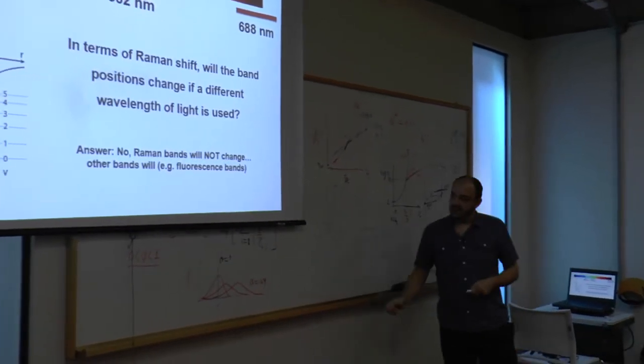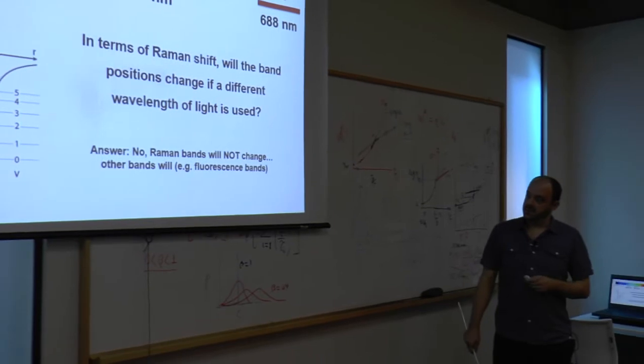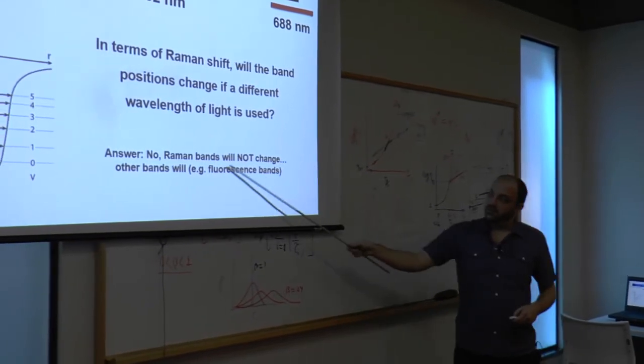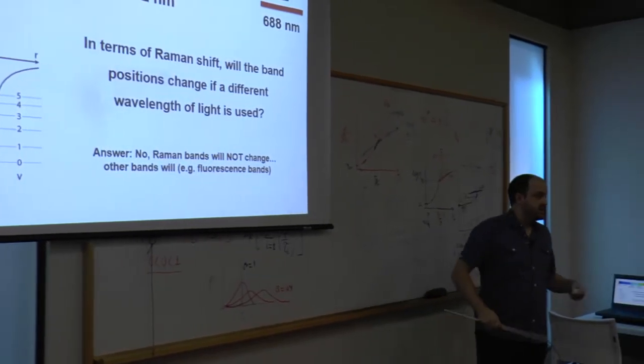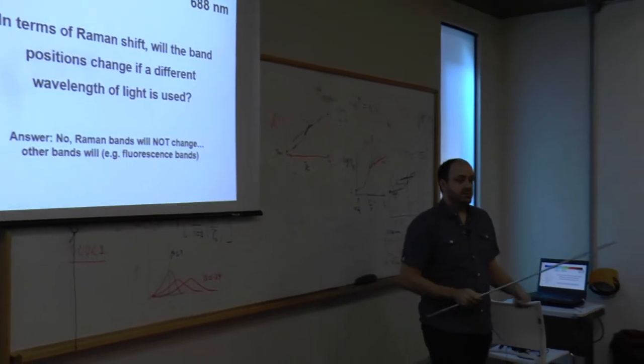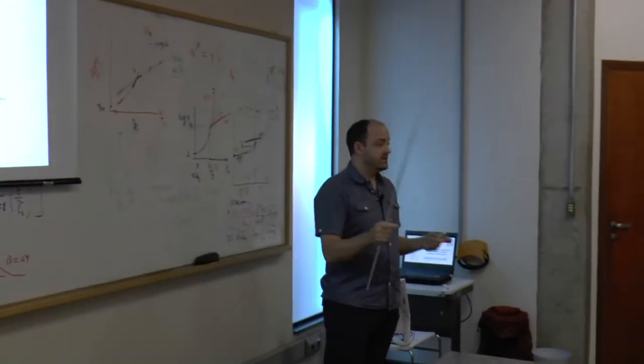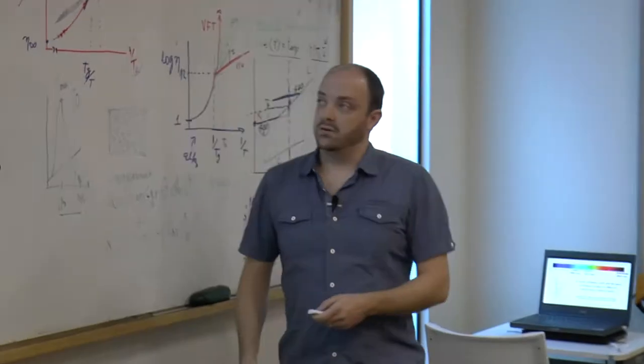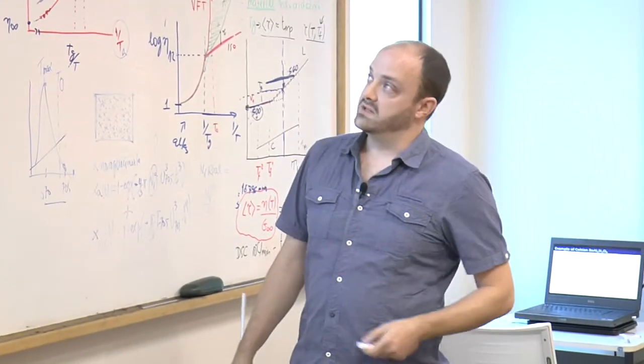But some other bands, and we'll see an example of this later on in the second half of this class, if they're related to fluorescence, they will change. So if you have some really fluorescent samples, you can play around and use different wavelengths of light to avoid that fluorescence and still get a high quality spectra.